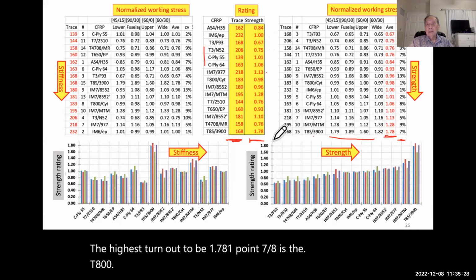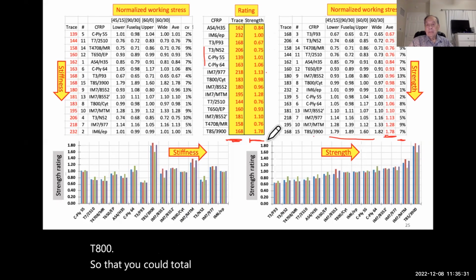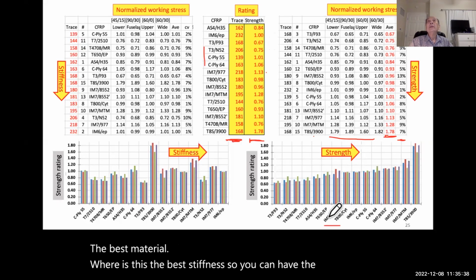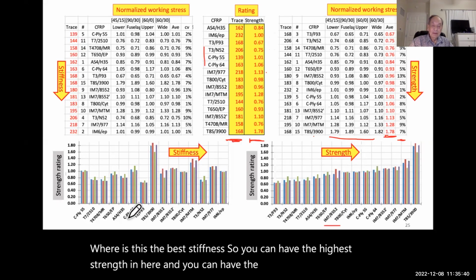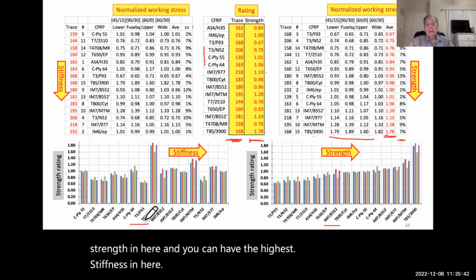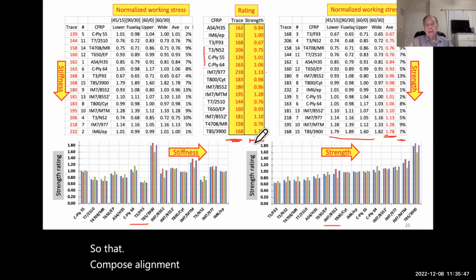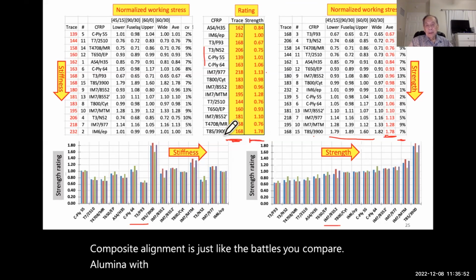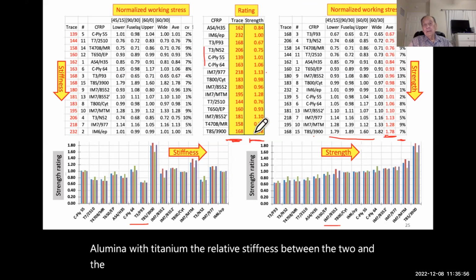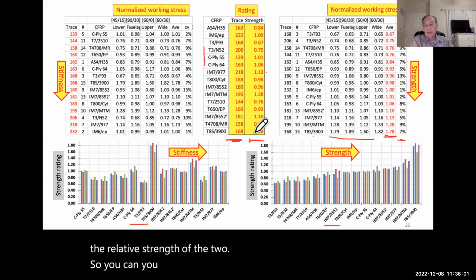So that you got total separation, the best material versus the best stiffness. So you can have the highest strength in here, and you can have the highest stiffness in here. So that composite laminate is just like metals. You compare aluminum with titanium, you know the relative stiffness between the two, and you know the relative strength of the two. So you can tell what it is.